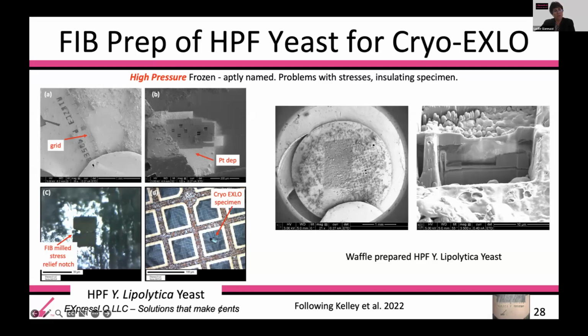conduction, so we put an extra grid on top of there. We put cryoplatinum deposited everywhere and onto the grid. And we were basically following the method of Kelly to do also this stress relief cut with the FIB. And we were able to get a cryo exlo specimen manipulated. Unfortunately, we weren't able to get this sample to the TEM.